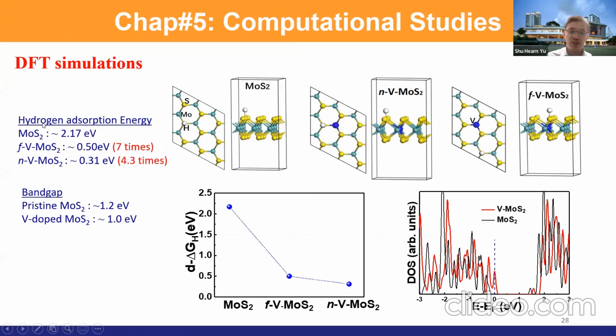And then we also do DFT simulation. In the DFT simulation, we try to do some case studies. Here, the blue color is vanadium. So this one is hydrogen near the vanadium, or in this one, hydrogen is further away from the vanadium. In both of these cases, the hydrogen adsorption energy is reduced. So as compared to pristine MoS2, the hydrogen adsorption energy is reduced, meaning the intrinsic activity is improved theoretically via DFT simulation after we dope in the vanadium atoms.